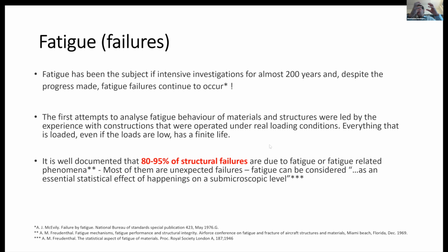If we see the failure surface, when it fails, the structure around it has cycles of damage, which are fatigue damage, and then the middle of the circle is rough, because at the end it fails at a bending moment that cannot be supported anymore, because the structure has a cross section which is less than what it was before the fatigue. And this is what we call a fatigue-related phenomenon. We'll see also later on some of this, but only to clarify the terms.